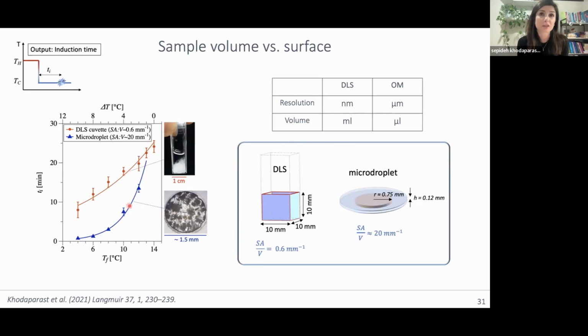But the result is telling you the opposite. Look at these numbers. This is the time to the observation of the first crystals. This is the final set temperature, and this is our crystallization temperature. When you're very close to this crystallization temperature, you have to wait around 30 minutes for the first crystals to be observed. But in all cases, you see the crystals in the first scenario much later